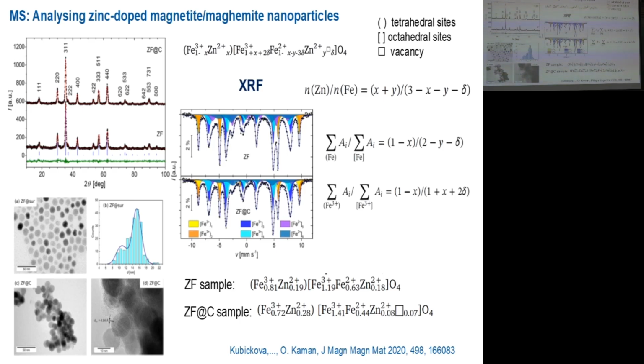But in this case, it was more complicated because of the presence of zinc. And so at the beginning, we had some material which can be generally described by such formula. So there are the tetrahedral sites, then there are the octahedral sites, and we have to assume that there is all the time some iron 3 plus and maybe some iron 2 plus, and there is the zinc, and the zinc 2 plus can be either in tetrahedral sites or in octahedral sites. And moreover, we cannot be sure that it is stoichiometric magnetite. Maybe some iron is missing because it's getting oxidized to iron 3 plus. So we have to introduce an unknown number of vacancies on octahedral sites.